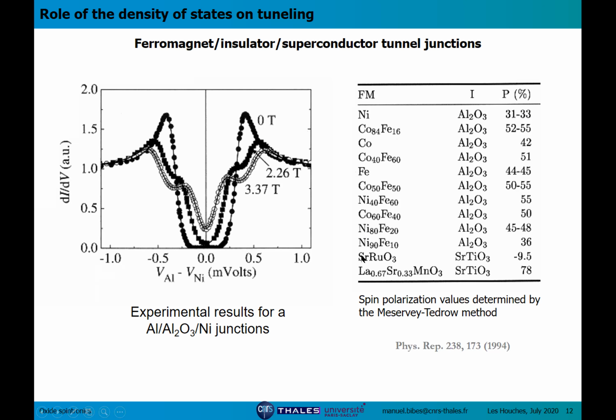And you also see data for oxides. So far, what I was telling you is more general metal spintronics or generalities on tunneling, and now I'm entering the oxide spintronics part. You see these first results of measurement of spin polarization in strontium ruthenate, which, as you know, is a ferromagnet, and has a negative spin polarization. Okay, that's the only negative number in this table. And lanthanum strontium manganite, LSMO, which has a very high spin polarization, 78%. And as I will show you, it can actually be even higher than that.